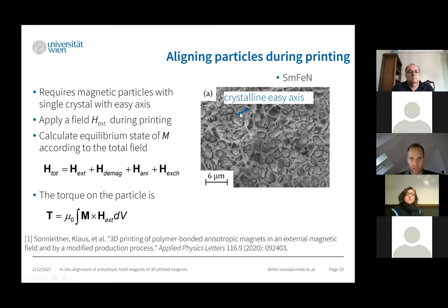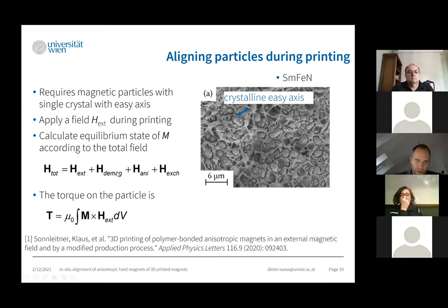How large is the mechanical torque? The mechanical torque can be calculated in the following way. We calculate from all these particles the total effective field on each particle, on each small element here, which is the sum of external field, demagnetization field, anisotropy field, and exchange field. Then we get an equilibrium magnetization, M, and the mechanical torque is then, it's maybe simpler than one might think, it's just the cross product M cross H.